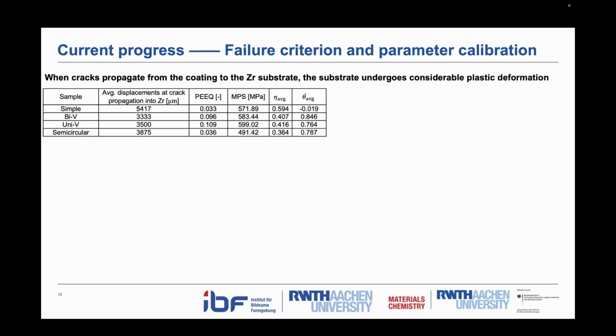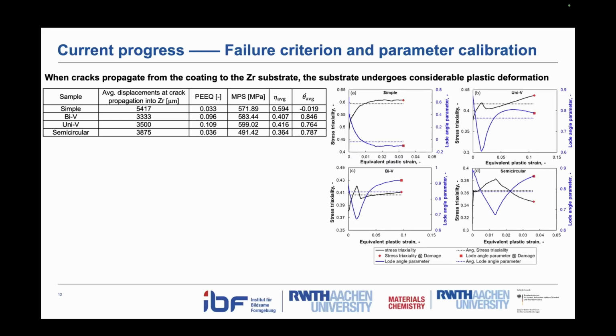And here shows our collected data at the critical moments. And here shows for all these 4 types of geometries, how the stress triaxiality and Lode angle parameters are involved with the equivalent plastic strain, which indicates we managed to cover a wide range of stress states.